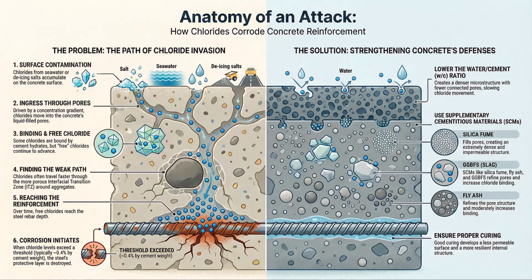Devastating. The second major error relates back to the severity of that constant salt bombardment. Underestimating the surface concentration. Correct. Underestimation of surface concentration, or CS. Designers often fail to account for the extremely high long-term CS that builds up, particularly in the splash and tidal zones. If you model using a standard global seawater value, but your structure is actually subject to a CS that's 50% higher because of evaporation, your prediction is going to fail. You have to model against the local, sustained, extreme concentration.